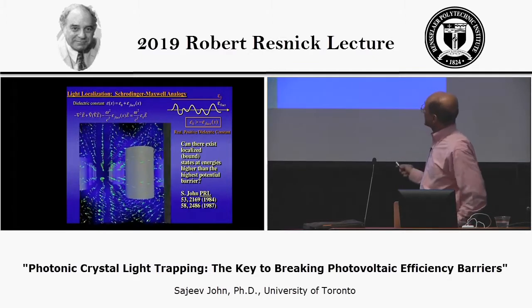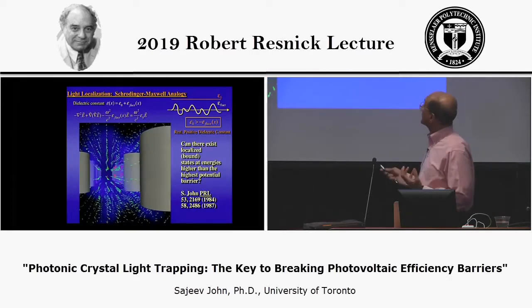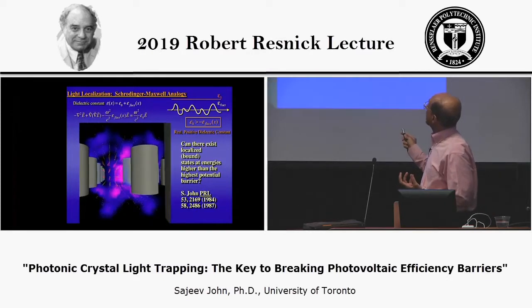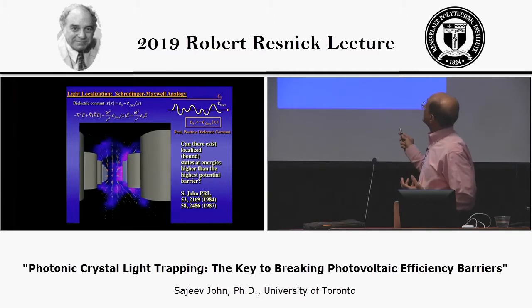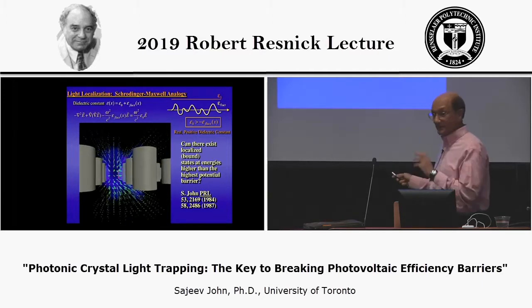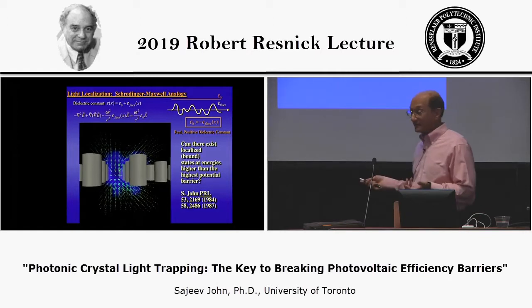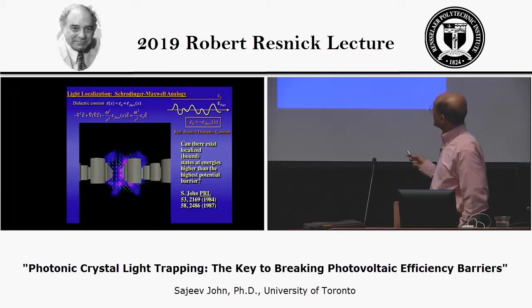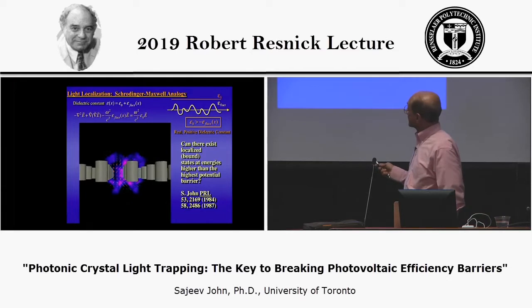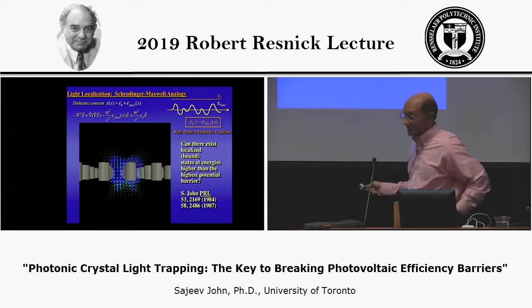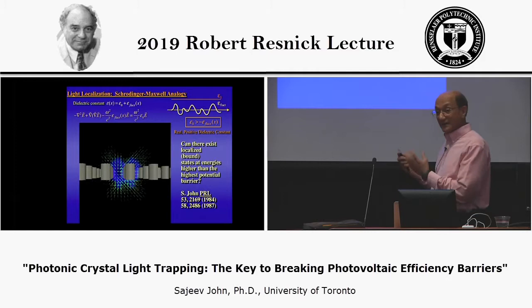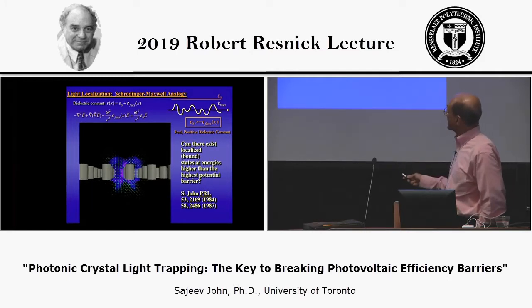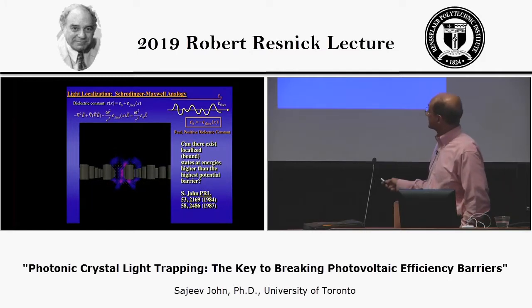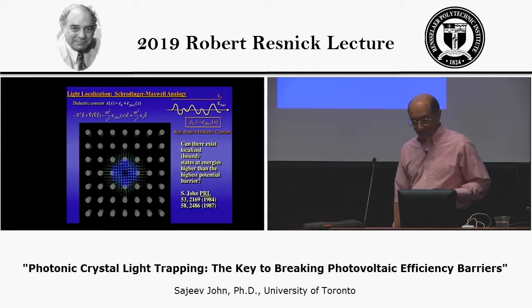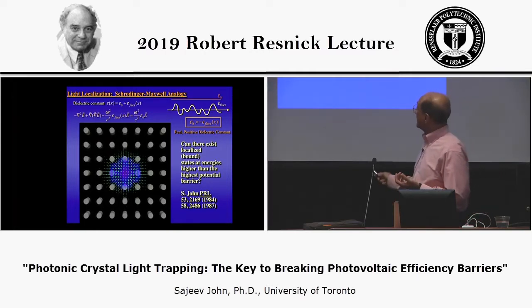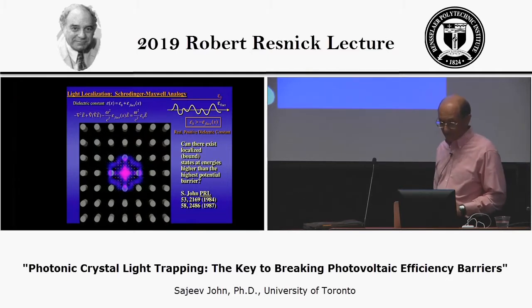But we were able to show that by arranging dielectric structures in the right way and creating a band gap in the spectrum of light, one could create these localized modes by then introducing some deviation from periodicity over and above the periodic structure. And this is a finite difference time domain simulation depicting a localized bound state of light around a defect in a photonic crystal. So the red and green arrows were the electric and magnetic fields, and the shading represents the energy density.